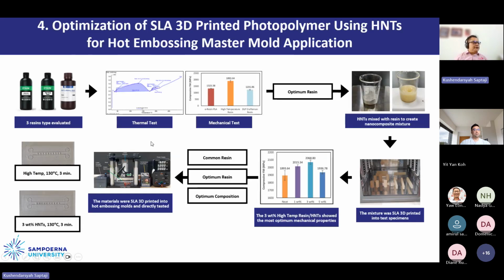The next result that I want to show is about how we try to optimize SLA 3D printing using additional HNT material. We try to create a master mold for hot embossing application. For this work, we evaluated 3 resins, and we performed the thermal test and also the mechanical test on these resins. From the mechanical test, we found that the high temperature resin has the best performance, so we use this resin as the one that we will add the HNT to.